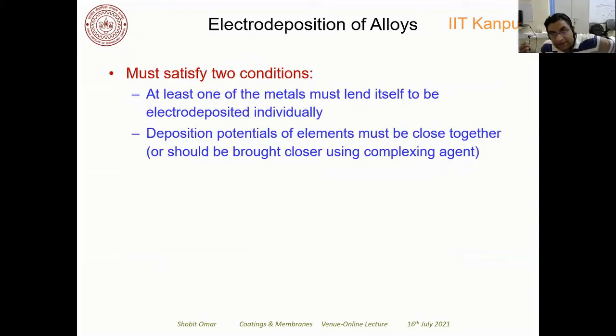So if you are electrochemically depositing an alloy, you have to satisfy two conditions. One of the metals should get deposited on the substrate. That is the main requirement for the alloy. One of the metals should get electrochemically deposited on the cathode side. The other thing is that the potential of the other element of the alloy should be very close to that of the remaining metal ion. So both the metal ions should have a very close deposition potential. Those are the two conditions.